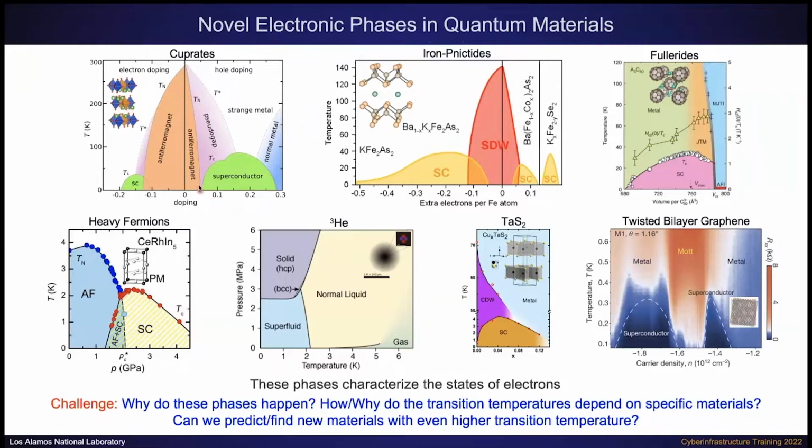And so here for the cuprates, let's say, this is some kind of perovskite-type structure, particularly you have octahedra of copper surrounded by oxygen, and some heavy elements in between to space out the layers. From this, if we add or remove electrons from the material and we look at its resistivity versus temperature, we find that first off, it starts out as a magnetic material. It's an antiferromagnet. If we dope it far enough, we get a high temperature superconductor.